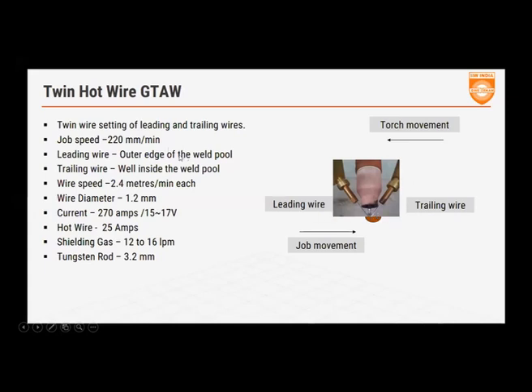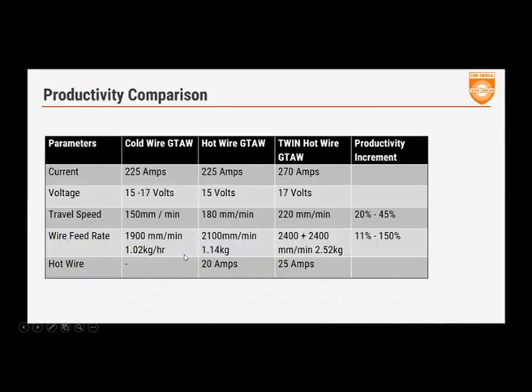If you look at a typical job speed of about 220 millimeters a minute, linear welding speed, 2 wires, each being fed at 2.4 meters per minute, wire diameters of 1.2 millimeters. Mind you, this is already on automation. Current levels were at about 270 amps, hot wire currents of about 25 amps, shielding gas, argon at about 12 to 16 LPM, and tungsten was about 3.2 mm.